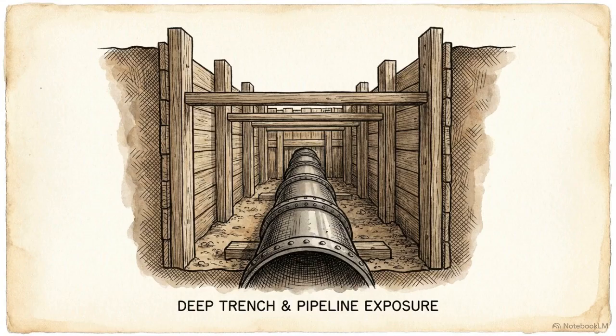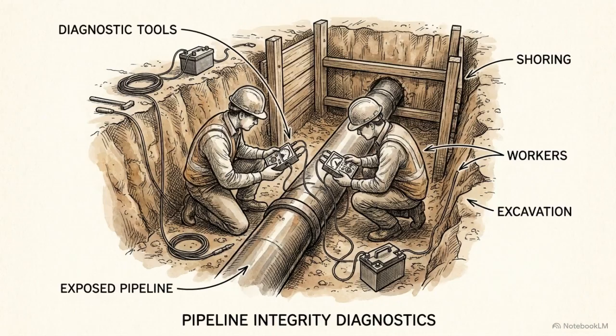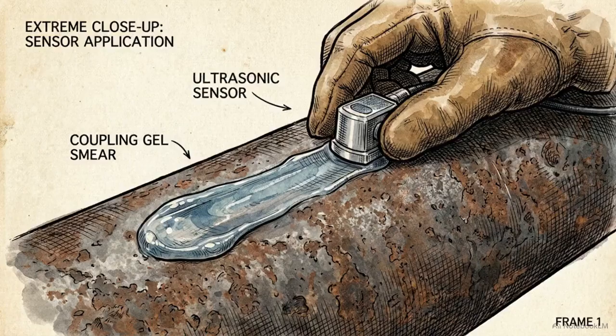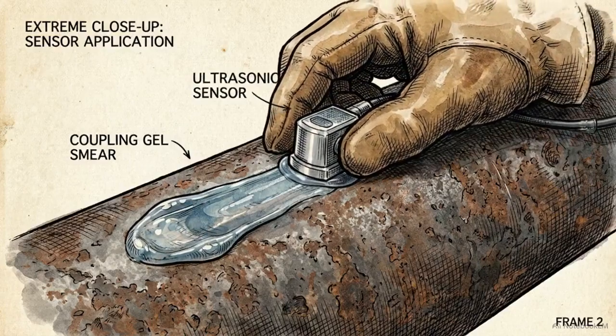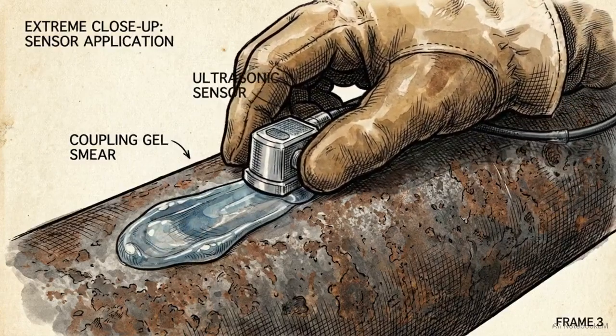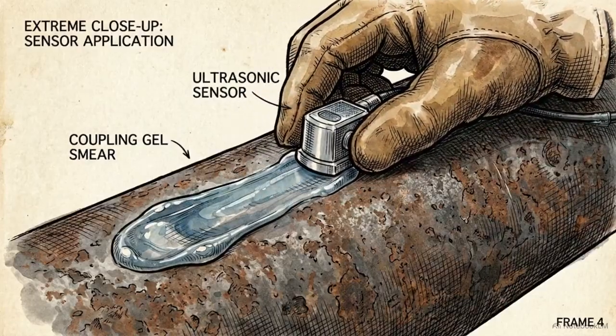With the surface coordinates locked, phase 3 begins: direct examination. Engineers excavate a targeted bell hole directly over the most severe DCVG readings. Once the pipe is exposed, the team conducts an assessment, utilizing ultrasonic testing to precisely measure any localized wall loss and pit depth caused by the external corrosion.